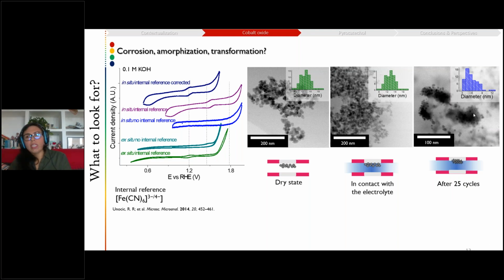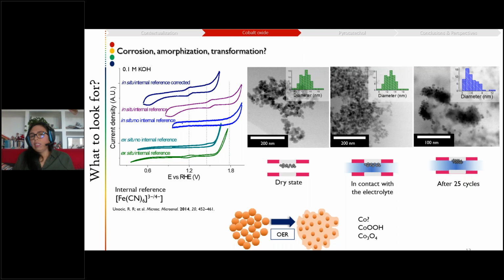But it also allows us to see in situ that upon 25 cycles, the overall size of the material seemed to have decreased towards 5 nanometers or so. And we seem to have two different contrasts, which leads us to think that there are different densities in the material. Since we didn't use any additive, neither carbon black nor Nafion, we know that what we have here must be our cobalt oxide. So we are sure that we are still seeing cobalt oxide, but what is happening? Is the cobalt going away?